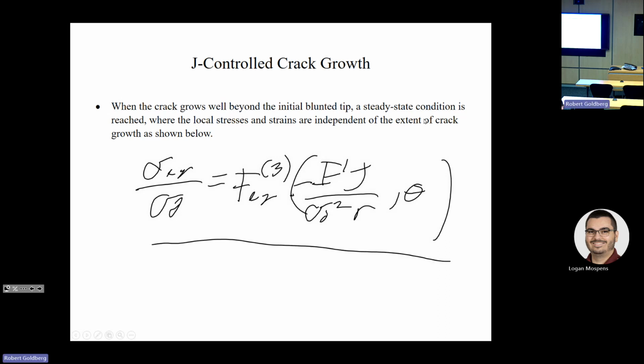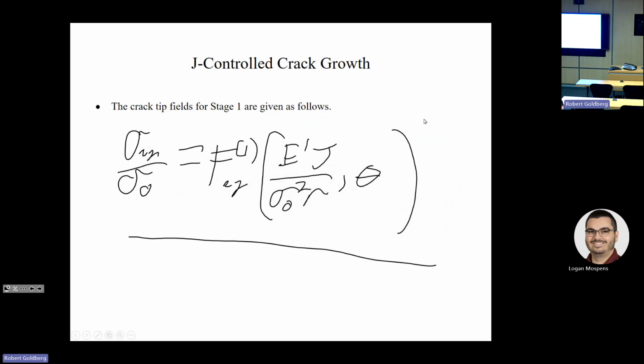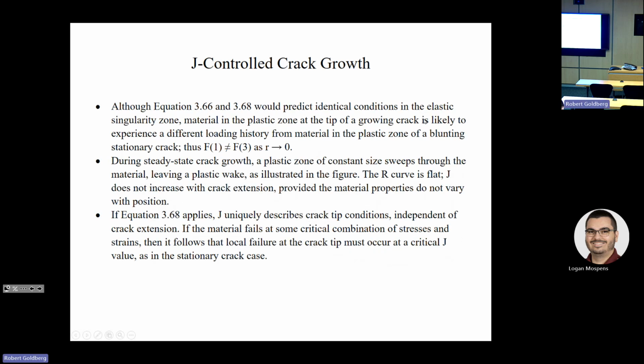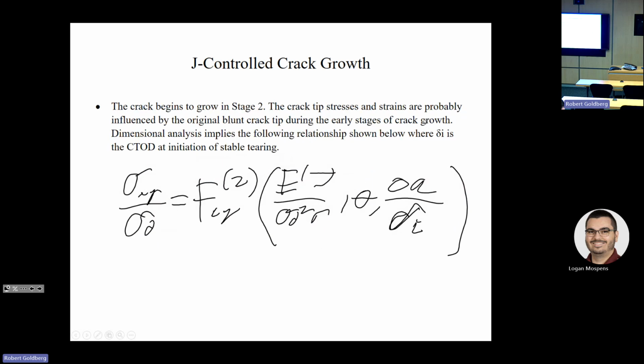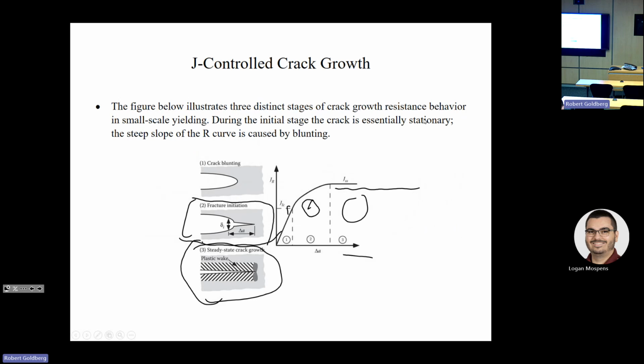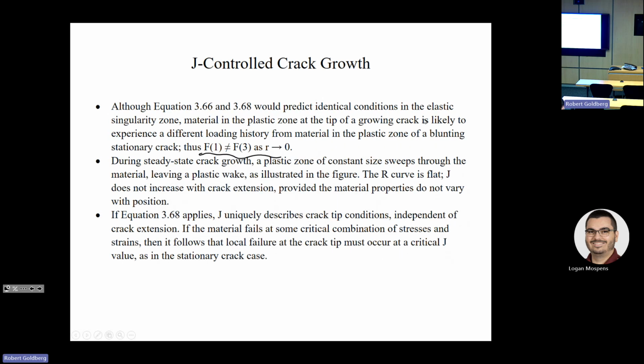So even though this equation and this equation would predict identical conditions in the elastic singularity zone, because of the history dependence, the material in the plastic zone at the tip of a growing crack is likely to experience a different loading history from material in the plastic zone of a blunting stationary crack. So these two functions are not equal as the radius goes to 0. And during steady state crack growth, a plastic zone of constant size, this idea here, sweeps through the material, leaving a plastic wake. The R curve's flat, J doesn't increase, as long as the material properties don't increase with position.